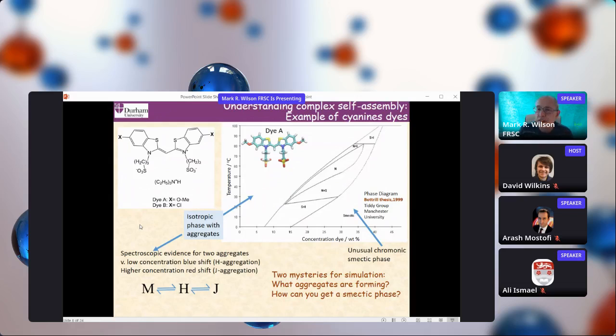This sort of methodology allows us to go back and understand many of the rather unclear things from the dye and drug literature in the past. I'll show you one example for a cyanine dye that's used in photography. This is the unusual sort of phase diagram that people found when they looked at dyes like this. At low concentrations, you get the same sort of aggregates in solution, but at higher concentrations, you get a phase diagram that looks like this. N here represents the nematic phase, which is obviously formed from long aggregates. But at very high concentrations, we have a totally different form of self-assembly to form something which the textures under an optical microscope tell us are smectic in terms of liquid crystal behavior. But it's very unclear what would be smectic in terms of the aggregates that form. So simulation should shed light on this.